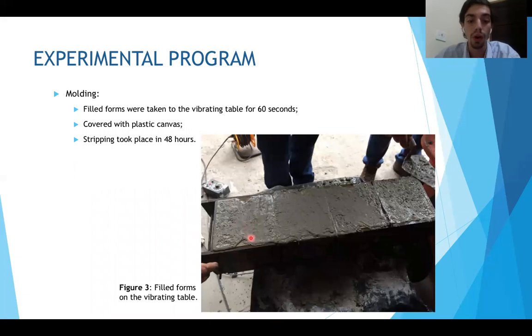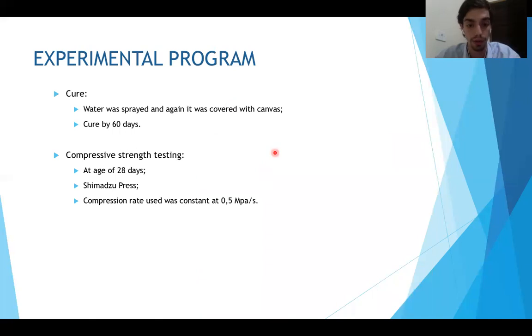All specimens were taken to the vibrating table for approximately 60 seconds and then covered with a plastic canvas. The stripping occurs after 48 hours. After the stripping, water was sprayed on the specimens that were again covered with plastic canvas for 60 days.